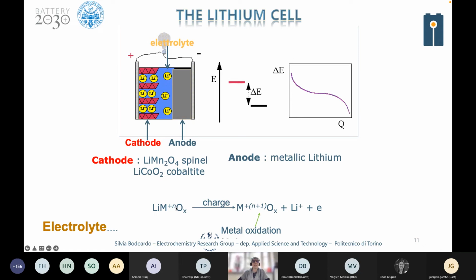During charge, we have the oxidation of the metal, which increases its oxidation state, as an example, from N to N plus 1. And as the negative charge remaining on oxygen does not change, of course, in order to keep the electroneutrality of the whole compound, one lithium ion is eliminated, deintercalated from the compound, and together with this we have the production of one electron that is used to produce electrical current that passes outside the cell. During discharge, we have the opposite, and of course the transition metal reduces its oxidation state, forming again the previous compound and reinserting the lithium ion inside.